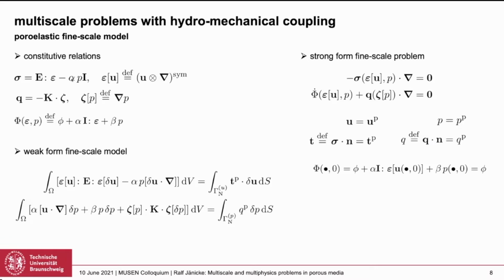Therefore, we cannot simply neglect fluid compressibility. Fluid transport is controlled here in the simplest case by linear Darcy law, where this theta is nothing else than the pore pressure. Here we have a permeability, which might be anisotropic. And we define the storage term, which is representing the amount of fluid stored in the porous medium, defined as the porosity, plus the amount of stored fluid, which is due to a deformation of the pore scale. If the pores increase, then more water can flow in. Or if I increase the pressure, then I can also, in a compressible case, pump in more water.